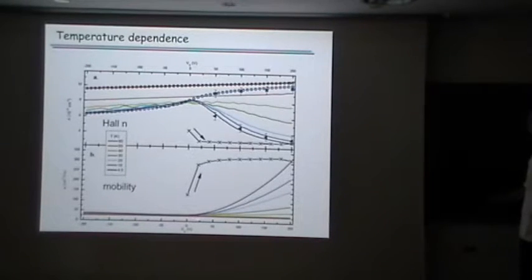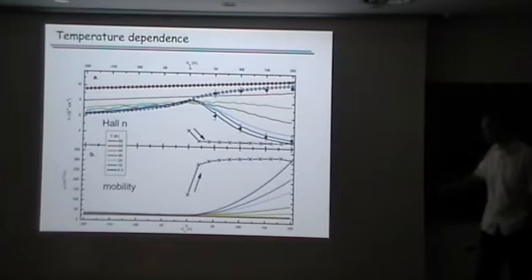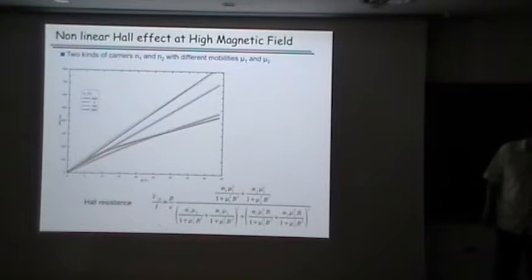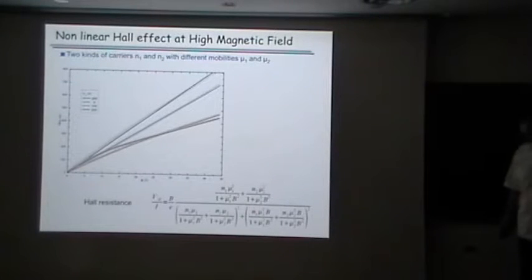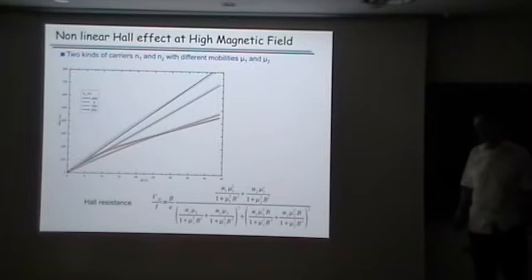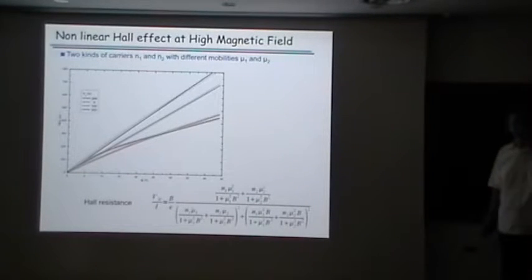And the mobility again, at high temperature the mobility is completely flat with the gate voltage, but at low temperature it rises up. Clearly there is something strange happening here. So we went to Toulouse to the high field facility to measure what's going on, and we measured the Hall effect. And as you can see here, the Hall effect at 0 voltage or at negative voltage is just linear. There's nothing special. But on positive voltage, there are clearly two slopes. That means that you have two types of carriers in the system.